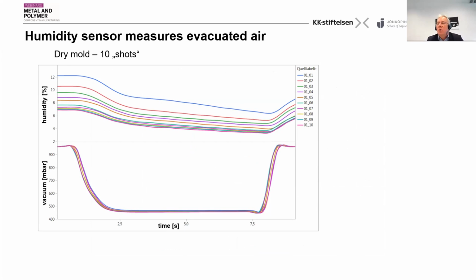Also, if you have a dry mold, parting agents are typically put into the die with water. The water is assumed to be evaporated by the heat of the die surface, but is it really true? You can see the vacuum pressure down there; the different colors are different shots, 10 shots behind each other. And you can see the vacuum pressure always shows the same. But here you can see the humidity of the evacuated air shows a big difference. In shot one, the die maybe was not that warm yet, and there is much more humidity in the evacuated air than in shot number 10. So you can see clearly there must also be a quality difference between the 10 shots, which would not be detected by the pure vacuum signal. So that's a big difference.